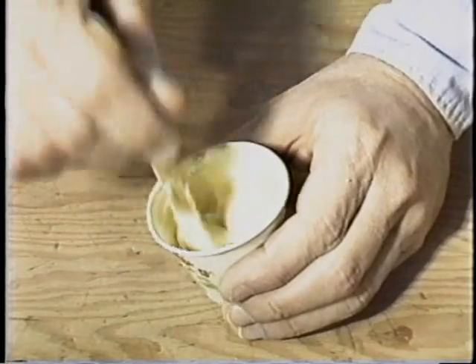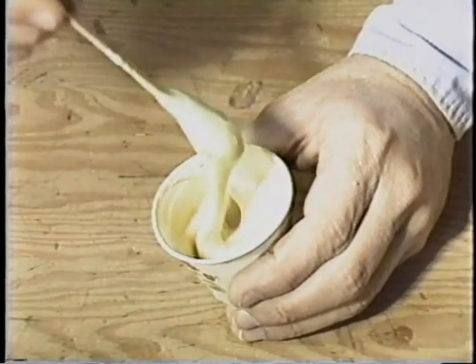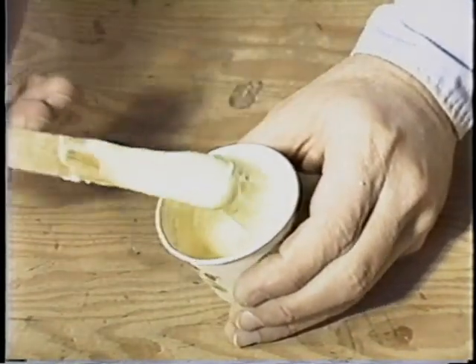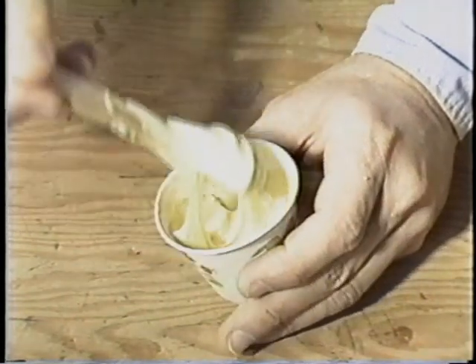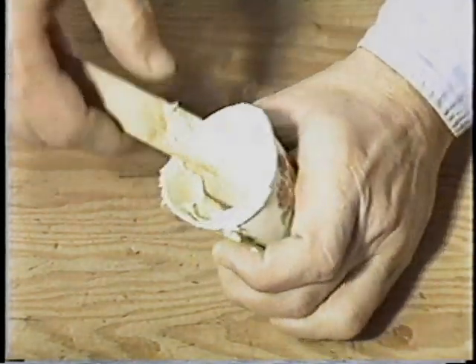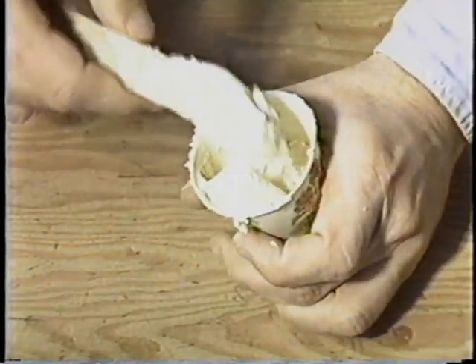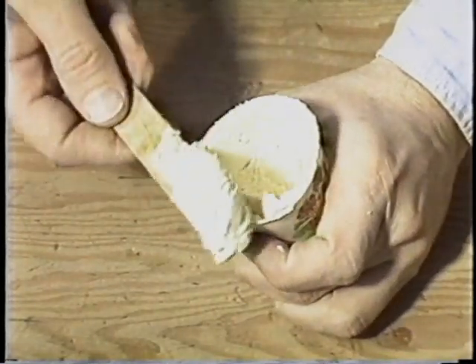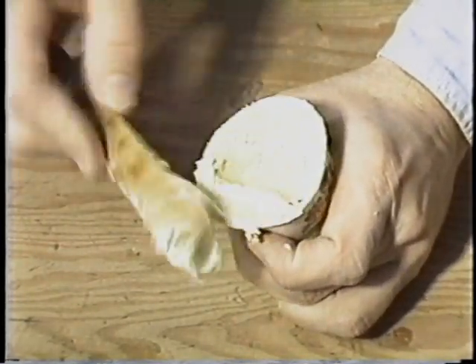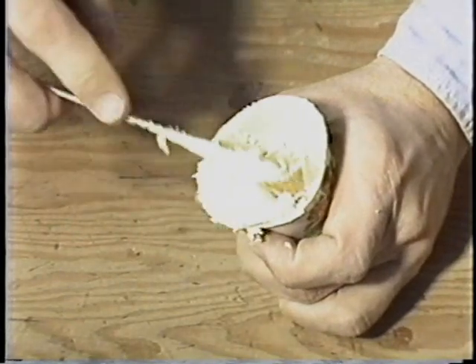Increase the mixture to 3 or 4 parts microballoons to 1 part epoxy, and you get wet micro. Thicker but still liquid in consistency, ideal for gluing joints. And when you add enough microballoons to achieve a consistency of peanut butter, you have dry micro, a mixture which produces virtually no structural quality, but an excellent lightweight filler for dents and gouges, akin to the body putty used in cars.